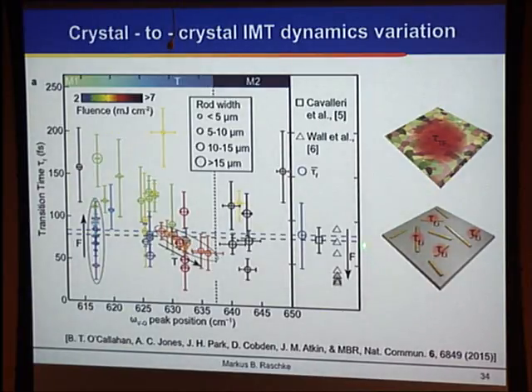I should say, though, that based on measurements of these polycrystalline thin films, there were dozens of papers which have tried to explain the single number of about 80 femtoseconds. Some people saw it as an indicator that it's an electronic-driven process, which indicates a Mott transition. Others saw it as phonon bottleneck limited, because a phonon optical cycle takes about this time scale, right? And nobody saw what enormous heterogeneity underlies that: some crystals can transition way faster than what a phonon bottleneck would suggest, but others are extremely slow.